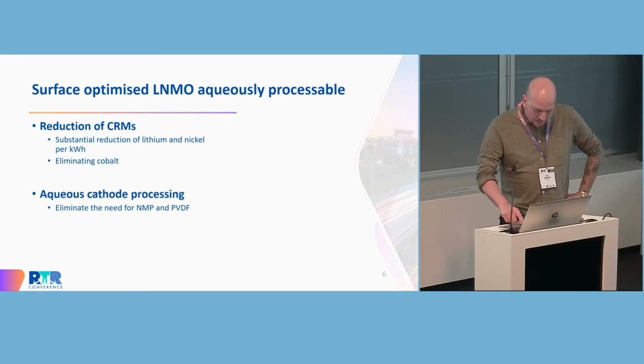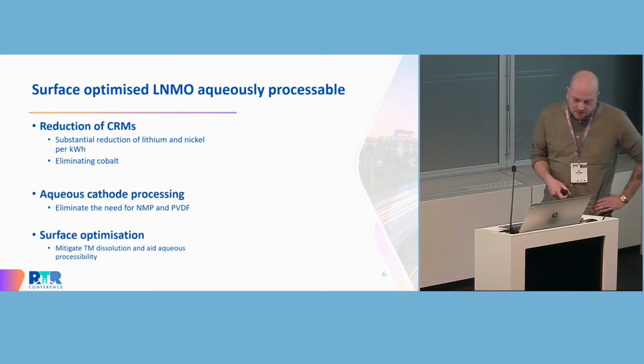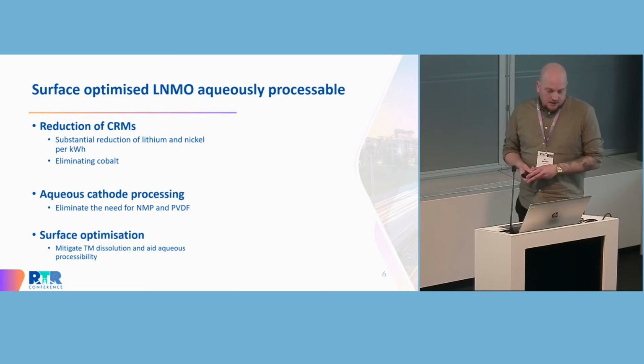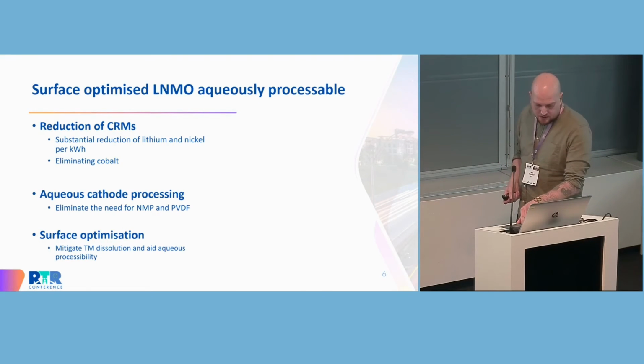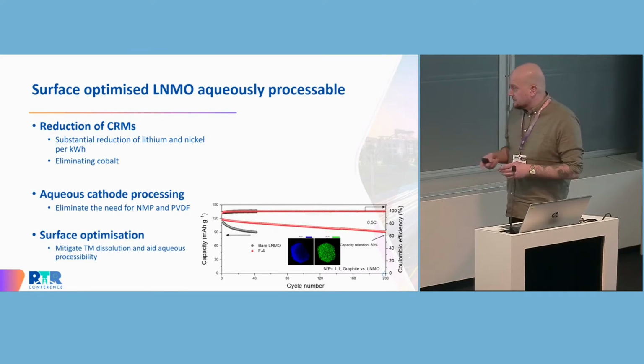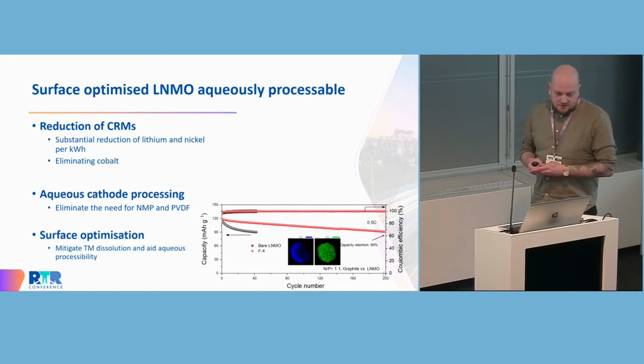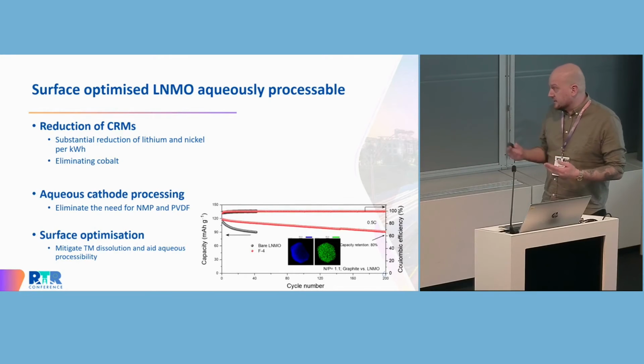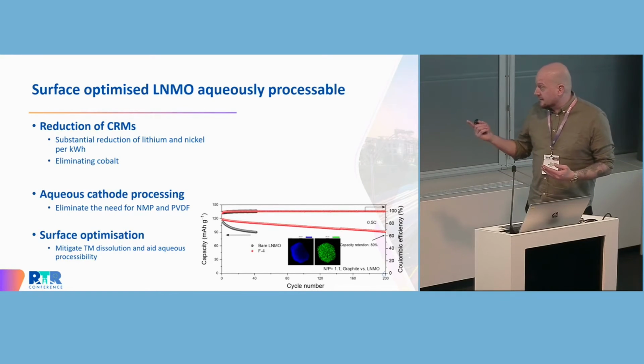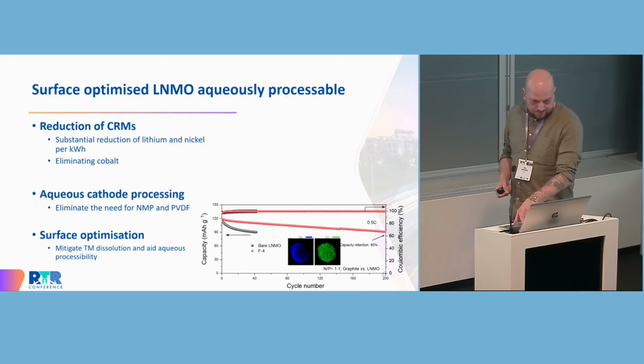A further highlight here that we already achieved is surface optimization. Our colleagues from Spain have worked on coating the LNMO material with a so far non-disclosed coating material, which also should mitigate transition metal dissolution and aid further the aqueous processing and also stabilize the system quite a lot.